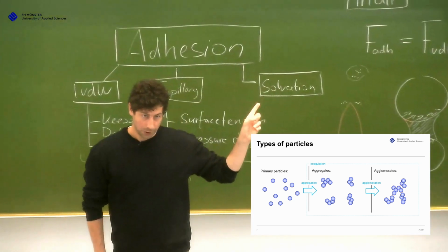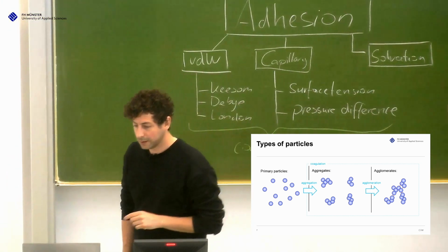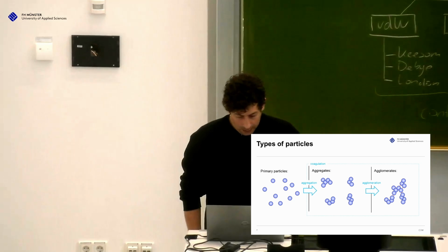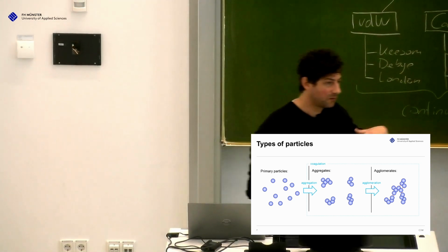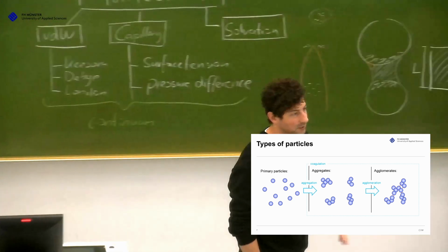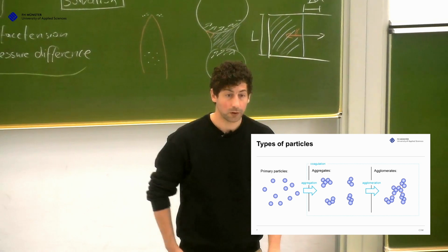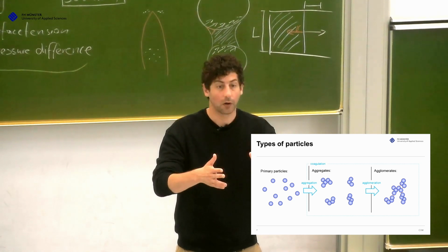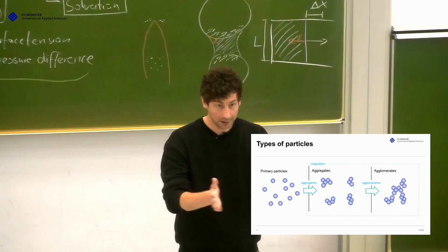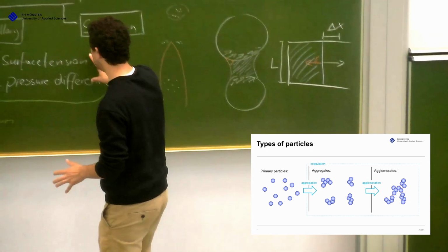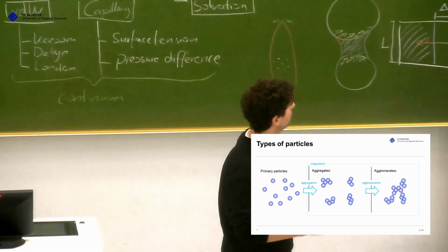This is my definition. In the literature, you mostly don't find a definition which is this sensitive, because mostly the terms aggregate and agglomerate are used vice versa. Aggregation could be the same as agglomeration, or mostly. But here it's important to distinguish, because I want you to understand how these agglomerates are built up. They are built up because aggregates adhere due to physical forces, and the aggregates themselves are chemically bonded primary particles.